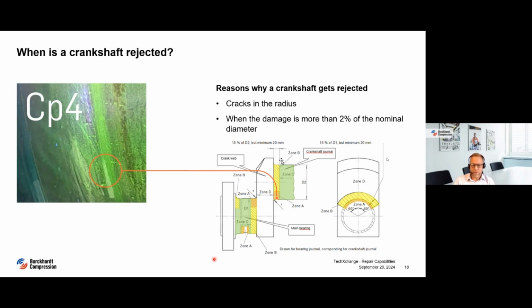When we have cracks in the radius zone A, or when the damage is more than 2% of the nominal diameter. In our case, the crankshaft would be scrapped at a diameter of 235. As I explained before, the nominal diameter was here 240 millimeters. Now I have already reached the end of my presentation, and I'm happy to hand over to Maddie.